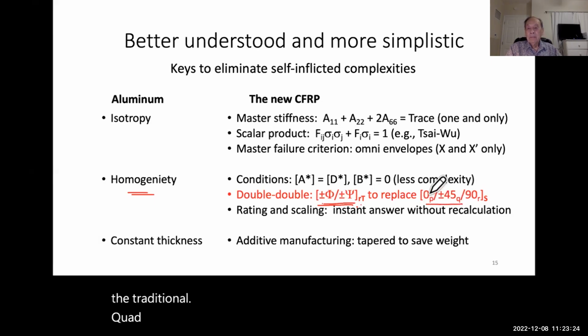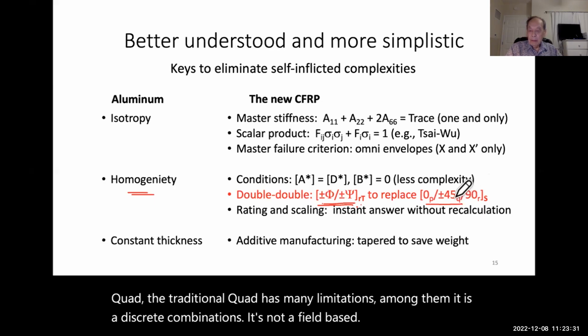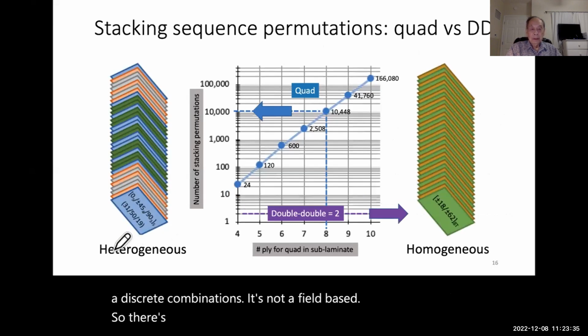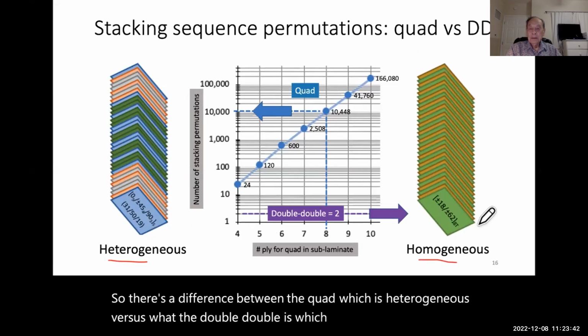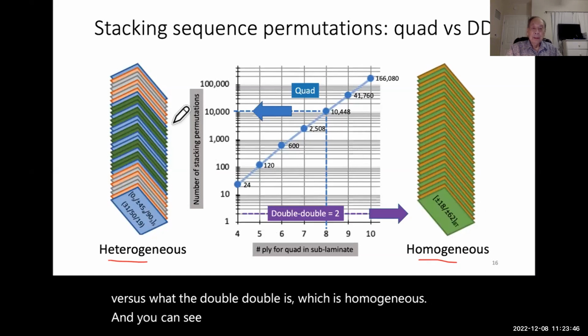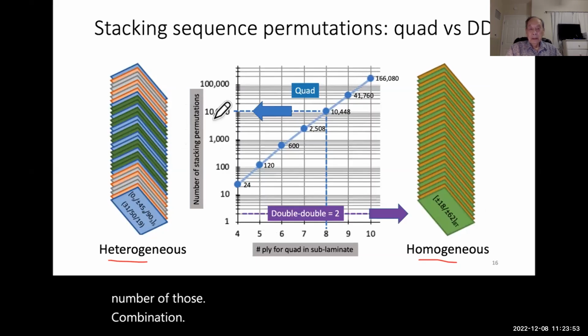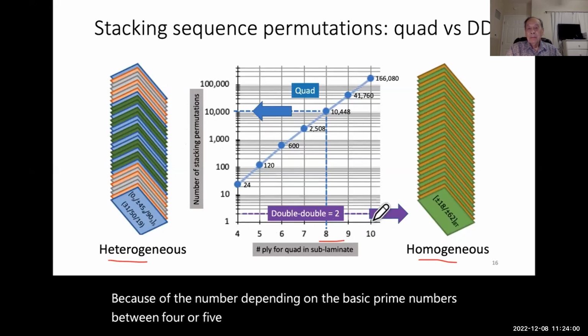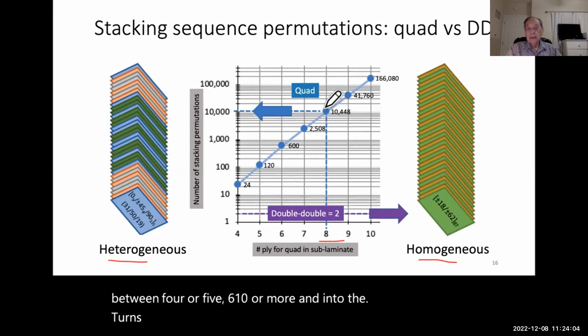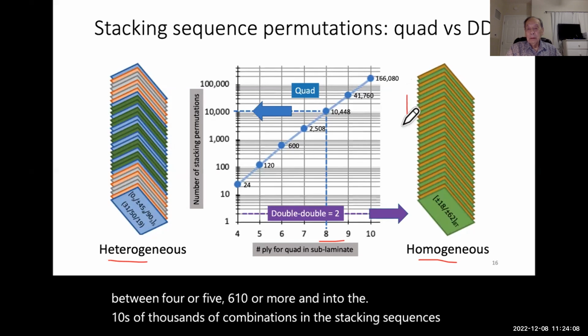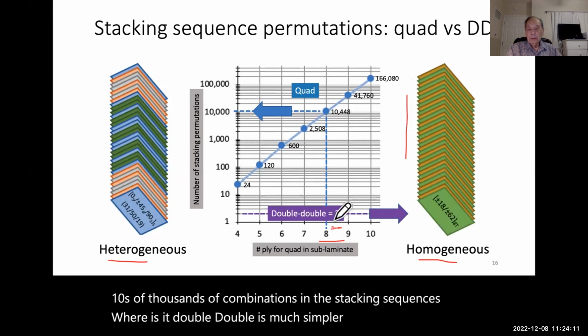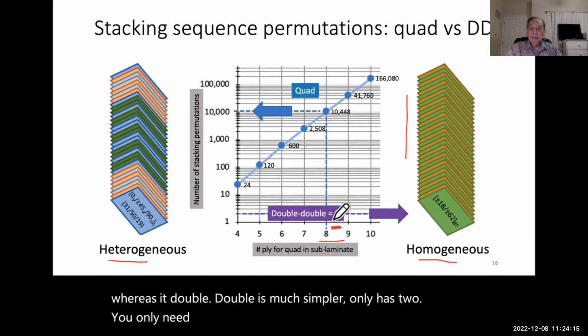The traditional quad has many limitations. Among them, it is a discrete combination. It's not field-based. So there's a difference between the quad, which is heterogeneous, versus what the double-double is, which is homogeneous. And you can see the quad is very complicated. Among them, the number of combinations, depending on the basic ply numbers between 4, 5, 6, 10 or more, goes into the tens of thousands of combinations in the stacking sequences. Whereas a double-double is much simpler. It only has 2. You only need to have 2 to be able to represent it.